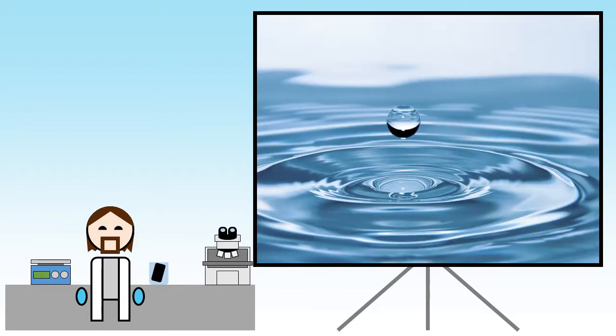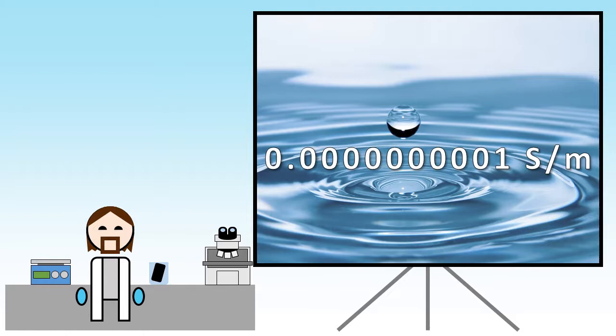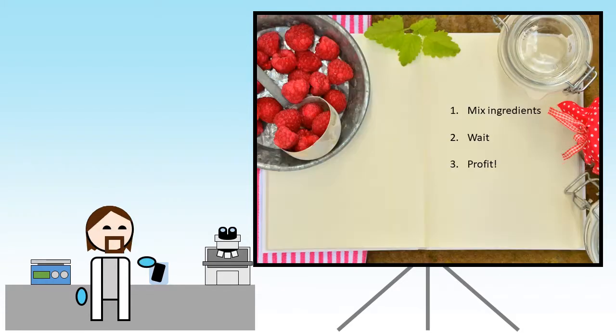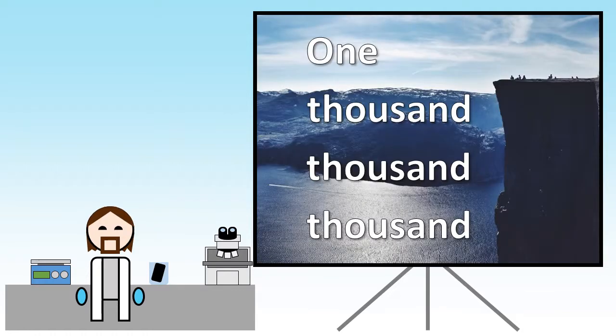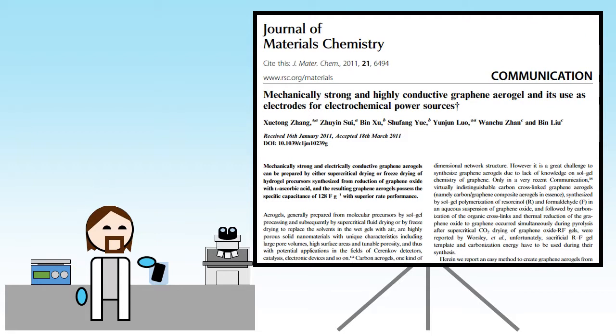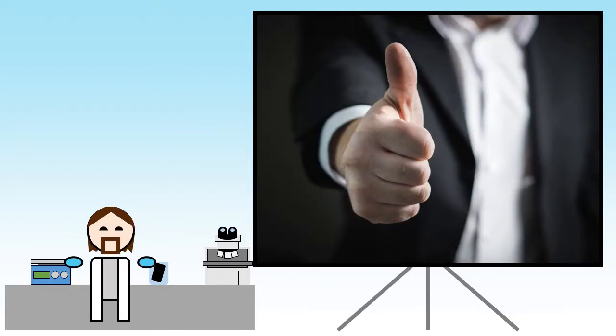But, as a comparison, the purified water we used in the experiment should have a conductivity of 10 to the power of minus 10 Siemens per meter. Our simple recipe has given us a reduced graphene oxide cake which is 1,000 million times more conductive than purified water. It's also only about 10 times less conductive than other researchers manage using a highly optimized process. Call that success.